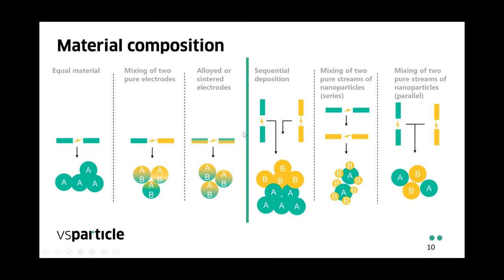An added flexibility of our technology is the ability to have a wide range of material compositions. On the left of this solid green line, I show the types of materials that can be prepared using a single G1 nanoparticle generator. If we equip it with electrodes of the same element, we get monometallic nanoparticles. If we mix and match the electrodes, we're able to get alloys with a varied composition between the two extremes. But if we pre-alloy our electrodes, we get nanoparticles with an elemental composition that aligns with the composition of the pre-alloyed electrodes.